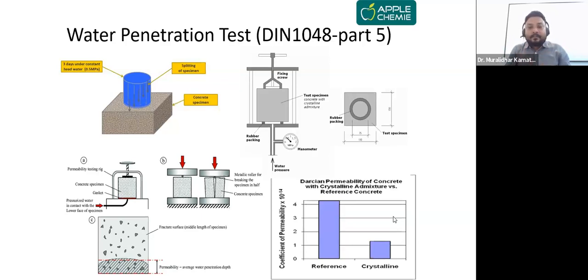After the fourth cycle, you are going to check the permeability K as per Darcy's law or Valenta's equation. As per Darcy's law or Valenta's equation, you are going to find out the coefficient of permeability with crystalline, K1, and without crystalline, K2. So (K1 minus K2) divided by K2 into 100 gives the coefficient of permeability in percentage. Generally the coefficient of permeability will be in the range of 10 raised to power minus 13 to minus 14, and it is going to reduce with the crystalline product.